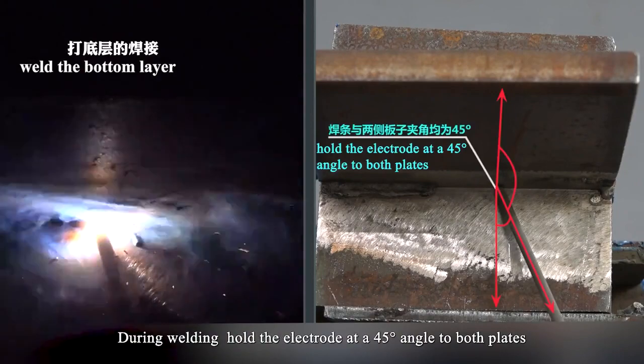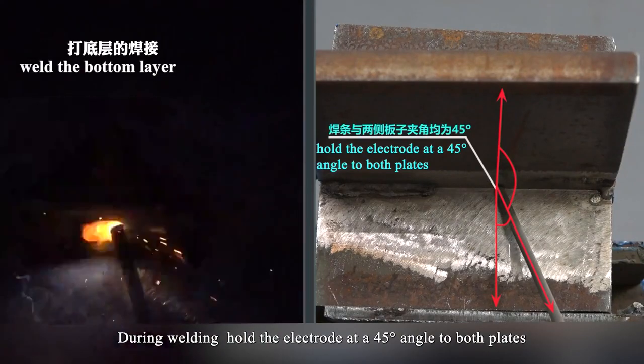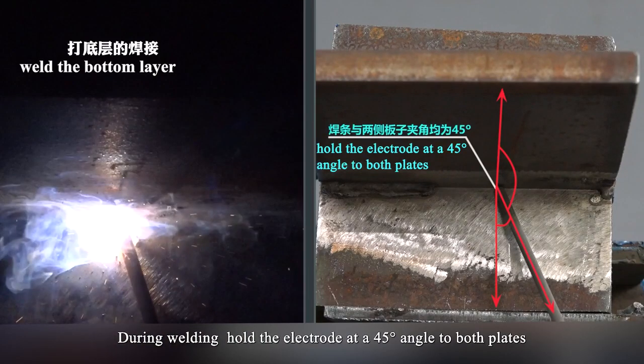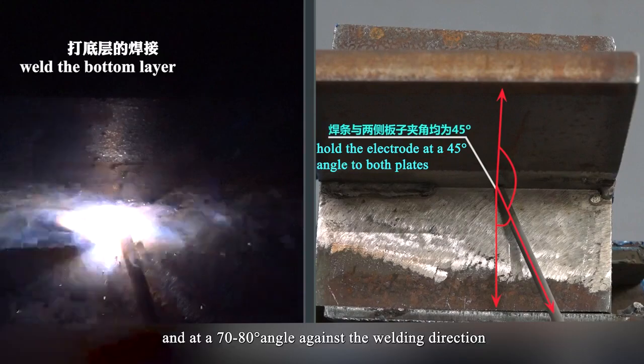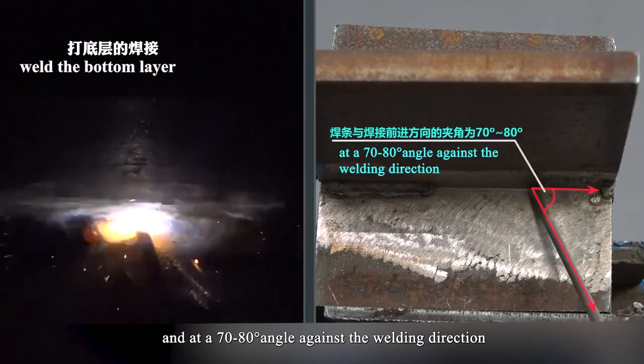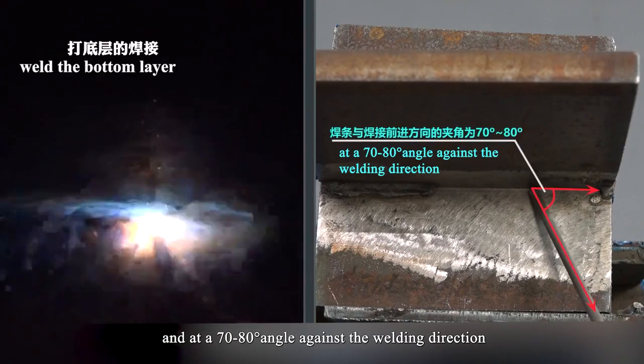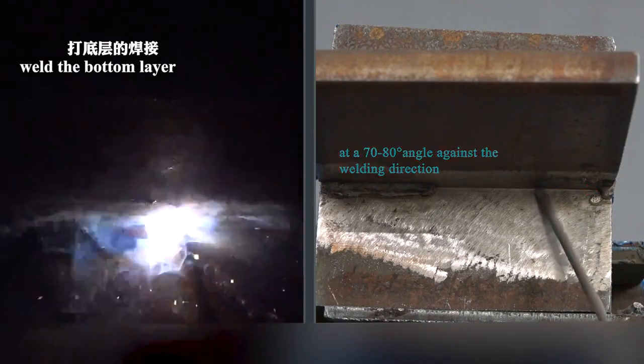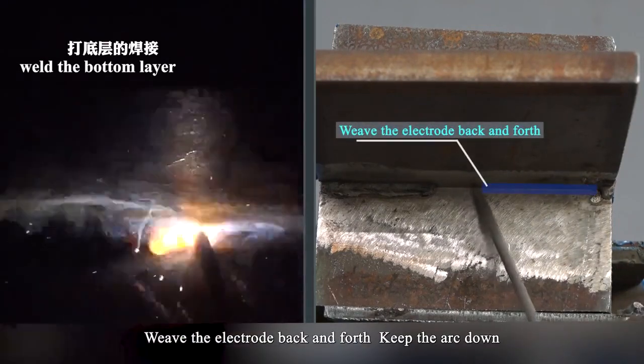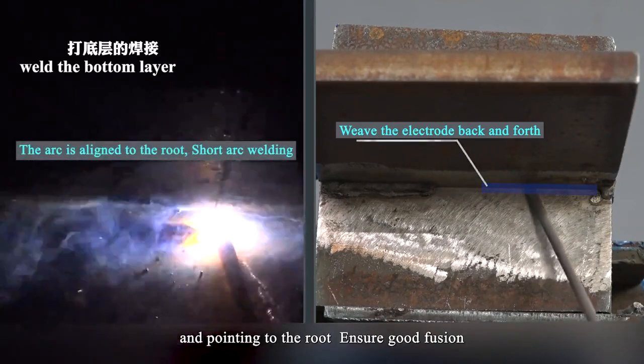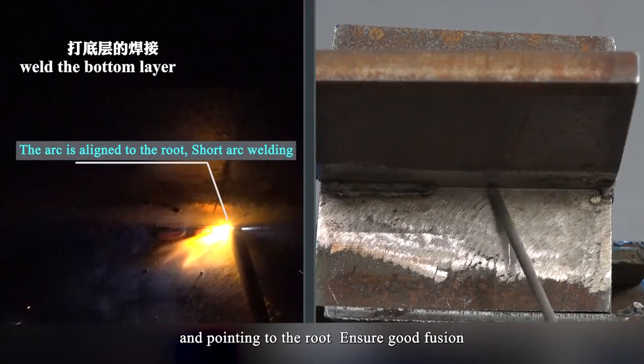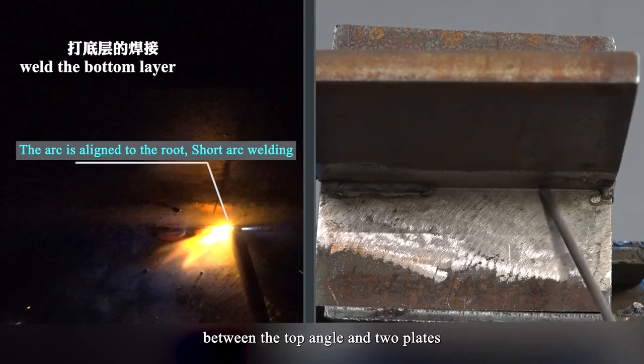During welding, hold the electrode at a 45-degree angle to both plates and at a 70 to 80-degree angle against the welding direction. Weave the electrode back and forth. Keep the arc down and pointing to the root. Ensure good fusion between the top angle and two plates.